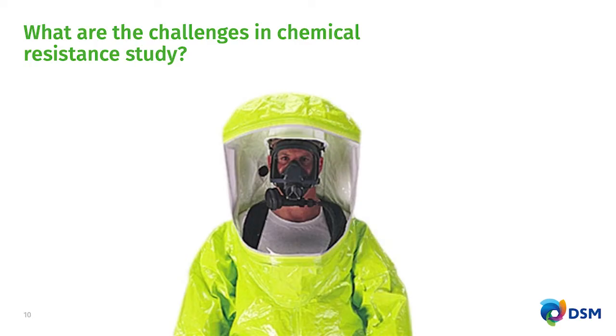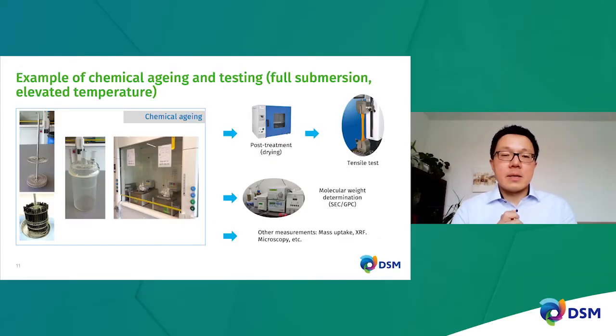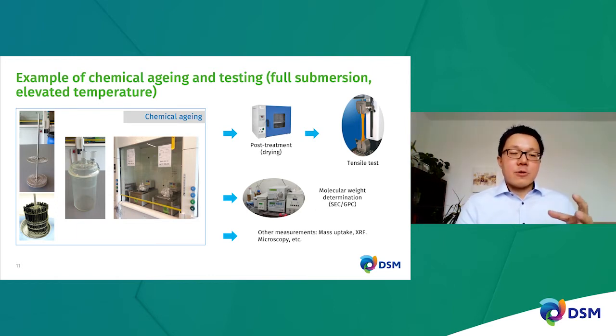What are the challenges in chemical resistance study in general? Before we go to that, let me present a little bit more on the typical chemical aging and testing that we do at our lab. If you are doing chemical aging, usually we use, for example, a standard representative form of plastics in the form of a tensile bar, and we place this tensile bar in a sample tray, and the sample tray will be placed in a glass jar. The glass jar will be filled with automotive fluids, and then we put that glass jar into an oil bath and increase the temperature, and we start aging, right?